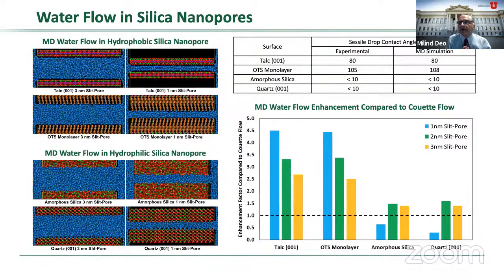We did some experiments as well as models, again, molecular dynamic models with different surfaces. So talc, which is an OTS, which is silane, so we looked at sessile drop contact angles, both with MD simulations and experimental, and we were able to match them reasonably well. So these are hydrophobic and these are hydrophilic surfaces, the amorphous silica and quartz.